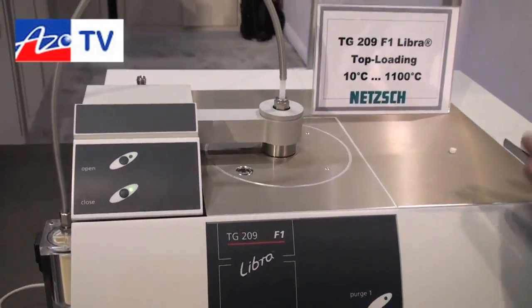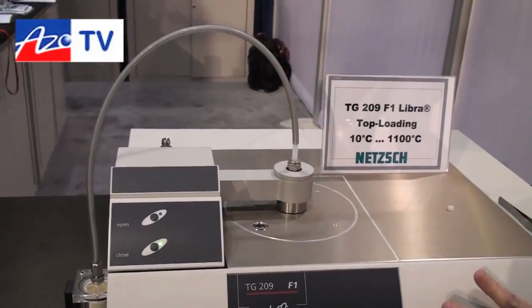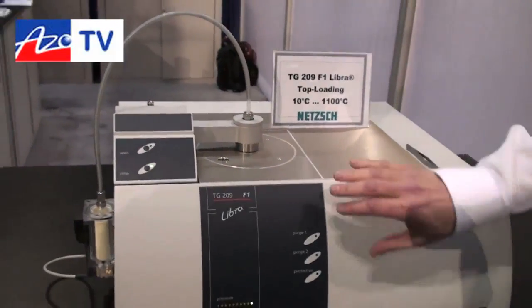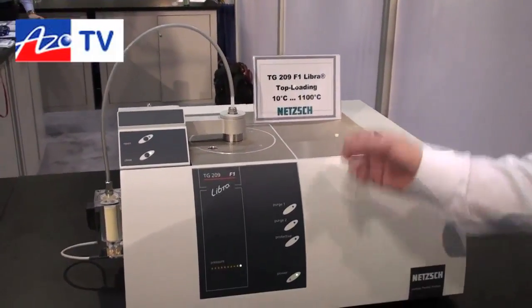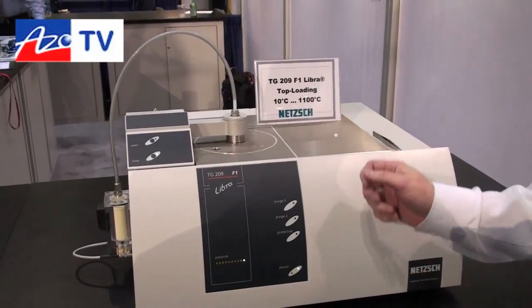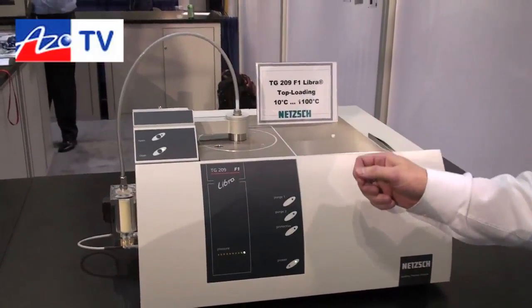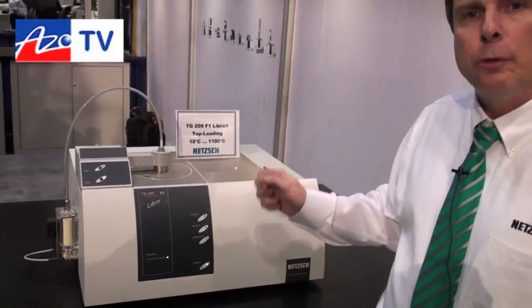So in this instrument, we have a balance in the chassis that rides below a furnace, and then we have a sample carrier that extends up into the furnace. We put our sample on that sample carrier, and then we normally heat the sample and we measure the mass loss steps that occur as we heat the sample.